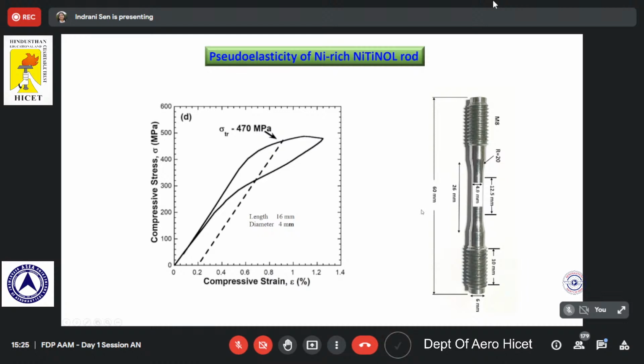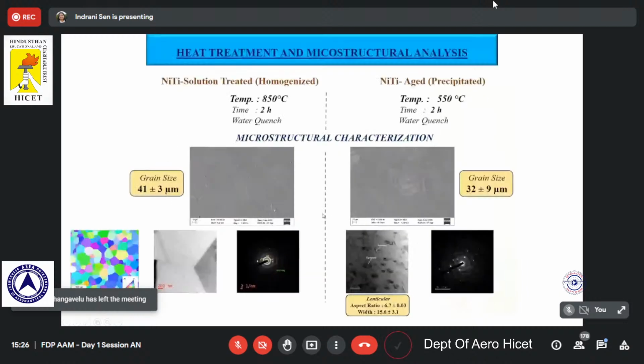Now, this material, when we are trying to age, we have something in mind. We understood that if we are aging it at a temperature higher than 300 degrees centigrade, it is supposed to form some precipitates. Some nickel-rich precipitates like Ni4Ti3 are supposed to form. So obviously, the microstructure is changing, the phase is changing. Now, let's see what happens to the pseudoelastic characteristics.